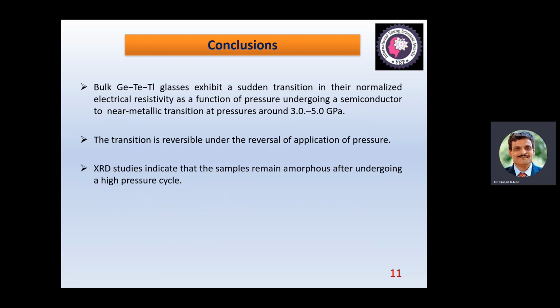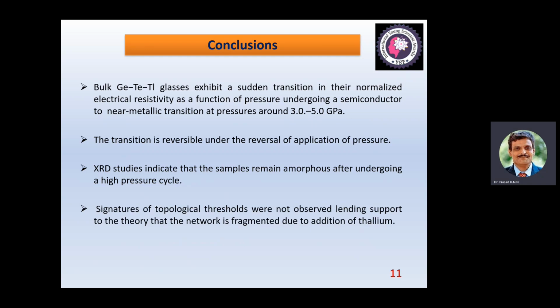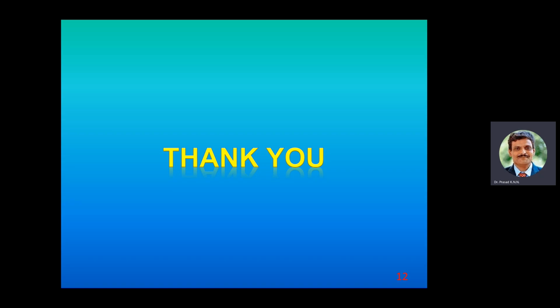XRD studies confirm that the samples remain amorphous even after undergoing a very high pressure cycle. Signatures of topological thresholds were not observed, lending support to the theory that the network is fragmented due to the addition of thallium. So I think with this, I will conclude my talk.